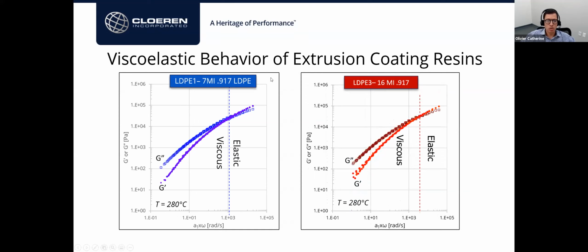And then finally, just to show that sometimes melt index can have very low meaning, here is a 16 MI LDPE. So even though the molecular structure is similar to that of LDPE1, it's a much lower molecular weight material. And we do see a delay in the crossover point compared to the blue material. However, we can still see a substantial melt elasticity compared to the blue material. So overall, even though this material has a much lower molecular weight and higher MI value, we can see a very similar viscoelastic pattern between the two.